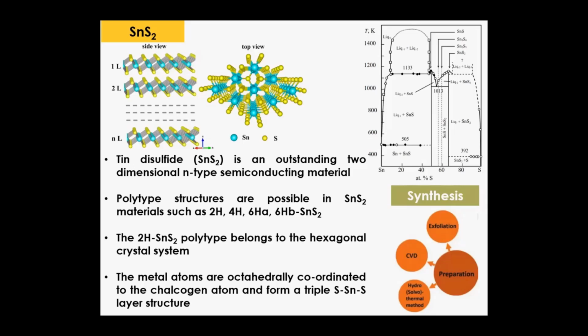Even in tin disulfide, we have many polytype structures. Tin disulfide shows 2H, 4H, and 6HA, 6HB polytypes. For two-dimensional material, we particularly concentrate on 2H because a very simple layer by layer structure is possible with this polytype. It shows hexagonal, so a layer by layer structure is possible. Here the picture shows the metal atoms are octahedrally coordinated to the chalcogenide atoms and form a triple S-Sn-S layer structure. So 2H shows S-Sn-S only.